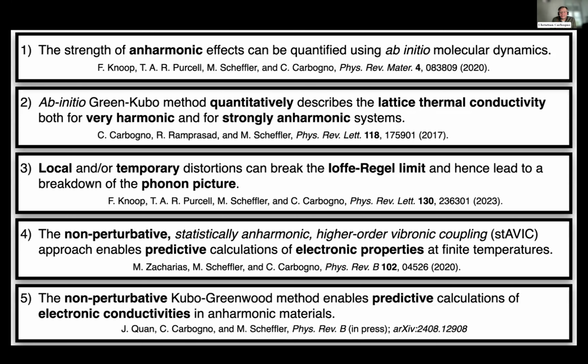I mean, to be honest, yes, that could be the case. You have to be aware, though, that the error bar in that kind of experiment is also plus minus 1 watt per meter Kelvin. And I think there are two experiments for copper iodide that we use to get this kind of result. I think we're speaking about regions of accuracy here where we would have to go beyond all kinds of density functional theory if we really want to go to that kind of digits and accuracy at the 0.1 watt per meter Kelvin level.